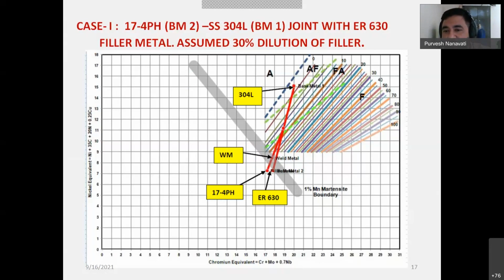without cracking or not. So here again we will calculate the chromium equivalent and nickel equivalent. Chromium equivalent contains chromium, molybdenum, and niobium of the base metal and for the filler metal we employed. Nickel equivalent considers nickel, carbon, nitrogen, and copper. So we mark the points of the composition on the WRC 1992 diagram. Say 304L will stand here, and 17-4 PH precipitation hardened grade will stand here.